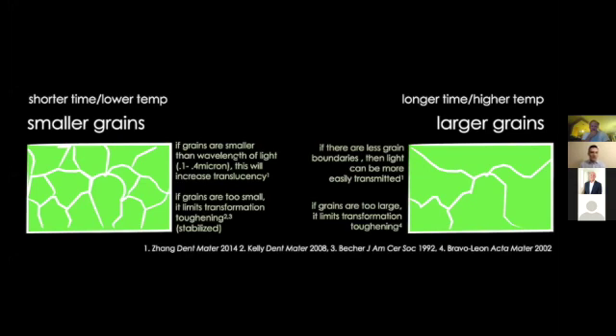And I think people have tried to play around with that to get properties that they want, because grain growth can also affect translucency and strength of zirconia. It affects these things in a tricky way, though. If the grains are really small, that can be good for translucency, because they're smaller than the wavelength of light, and then light can pass through. But you can also make grains really big, and that can make them more translucent, because then there are fewer grain boundaries, the boundaries between grains, and the grain boundaries are what stop the light from going through.